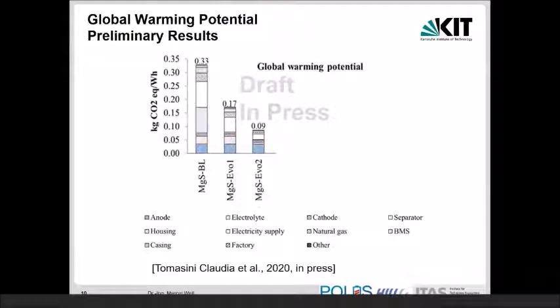Now it is absolutely better, and now even with the improvement regarding the separator and the electrolyte, it's really a relatively low value. And what does relatively low value mean? Just for the comparison, I put here the LFP battery system, and you see, at least from the feeling, that now with this theoretical improvement of the cell, we are at least in the range of this LFP system.